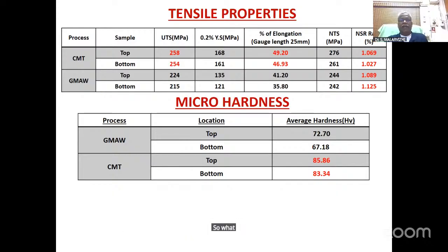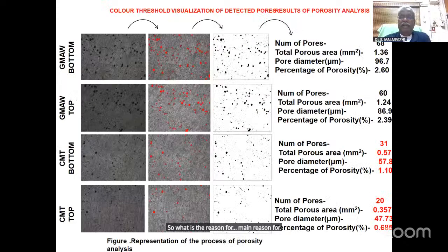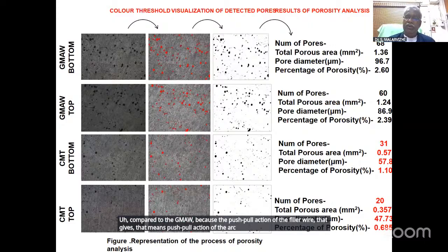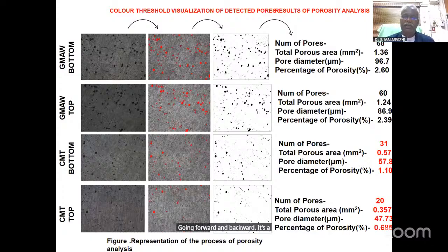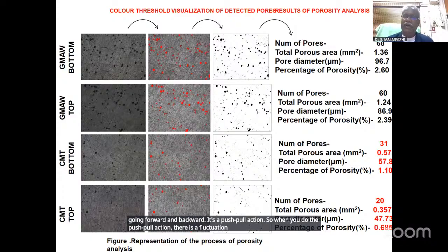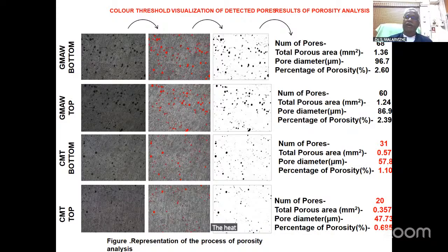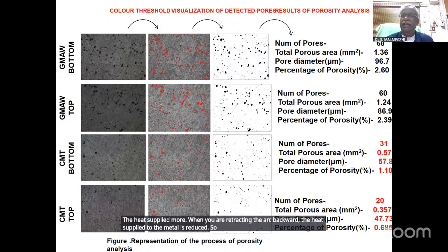So what is the main reason for the increase in hardness as well as strength? Then we went for the microstructural analysis. Finer grains are formed in the CMT compared to GMAW because of the push-pull action of the filler wire. That means the push-pull action of the arc. The arc is going forward and backward. When you do the push-pull action, there is a fluctuation in the heat input also. When the arc is moving towards the weld pool, the heat supplied is more. When you are retracting the arc backward, the heat supplied to the metal is reduced. So there is a fluctuation in the heat input.